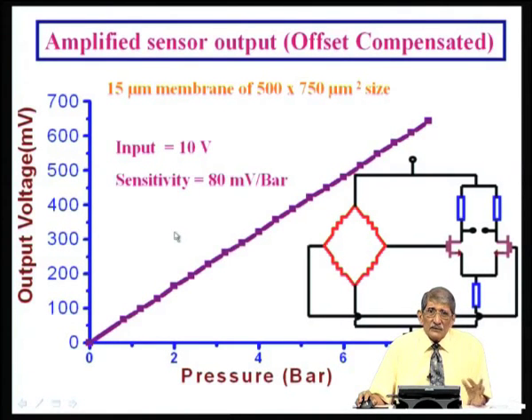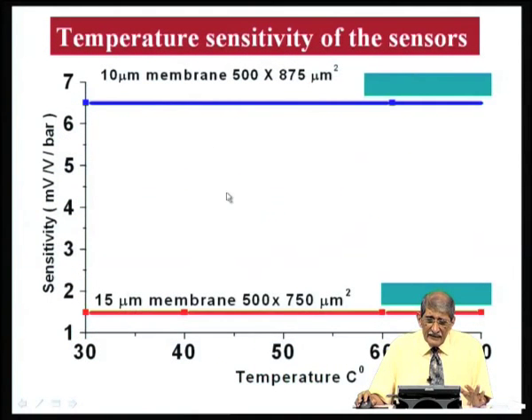This was initially run to check the optimization of the two processes, and if I take the sensitivity as a function of temperature, that is almost constant from 30 to 70 degrees centigrade. To show that the polycrystalline resistor, which is used as a piezoresistor, worked out very well for higher temperature operation.